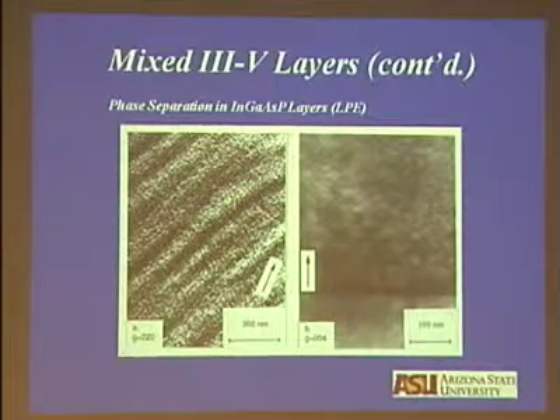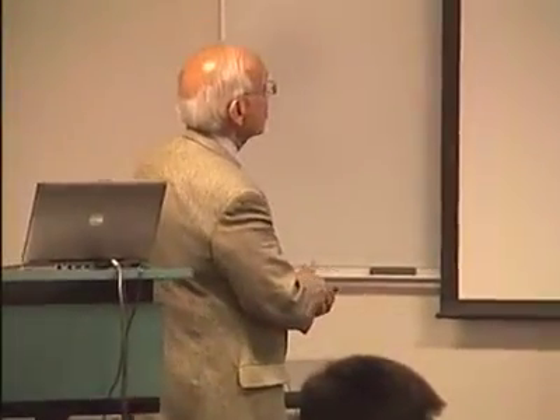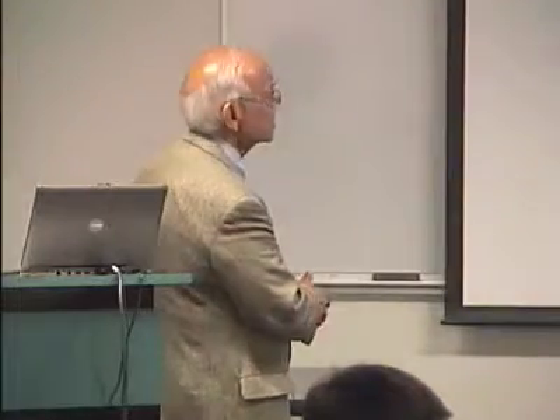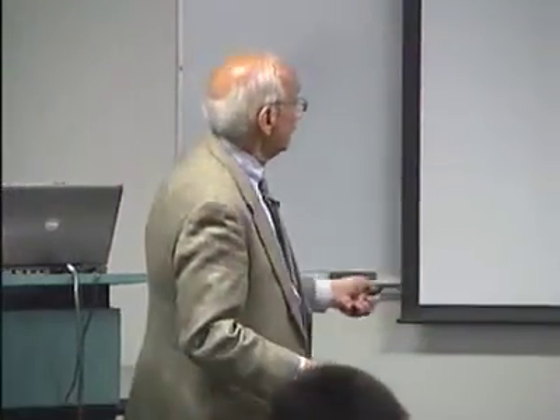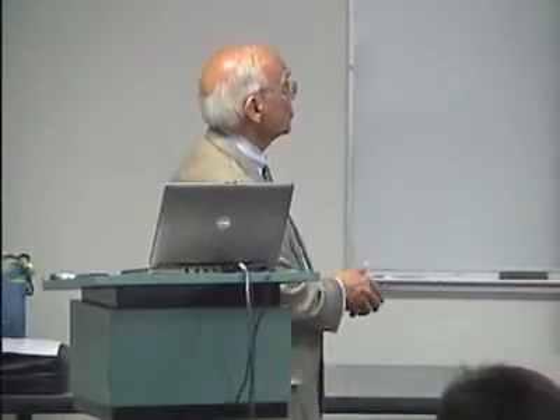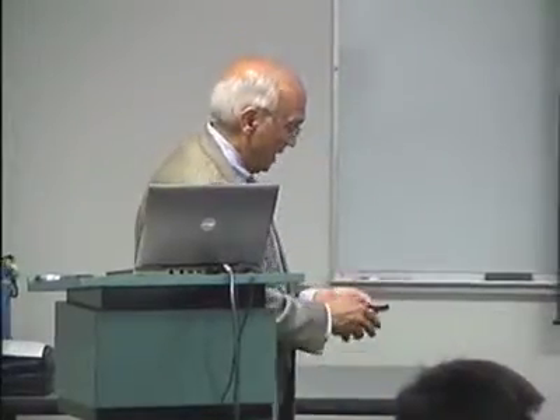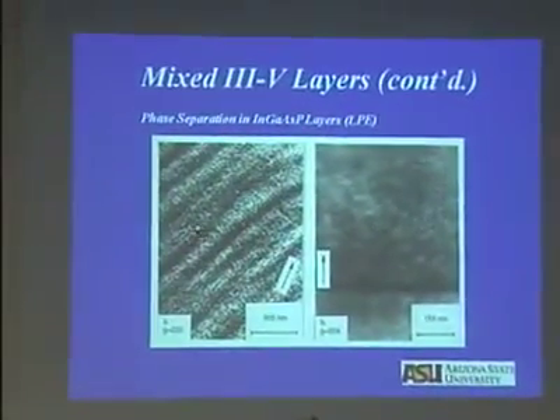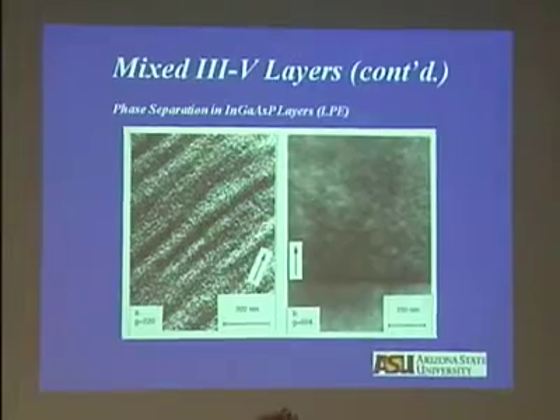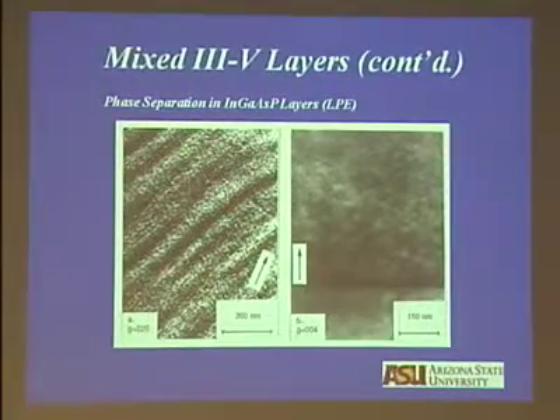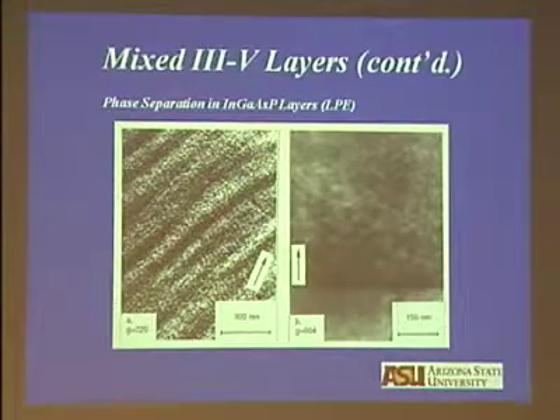What this suggests is that phase separation is two-dimensional in nature. It doesn't occur along the growth direction, but it occurs along the soft directions lying in the growth plane. If you have this arrangement, those directions happen to be 110 type. So what you conclude from these two micrographs: we have a fine scale speckle structure, whose wavelength we can determine. I'll show you in the next slide how we do it. And there is no phase separation along the growth direction. And you may ask, what is this dark contrast due to? When phase separation occurs, you produce biaxial strains at the interface. And that buckles the surface of your layer, and this dark contrast is due to that.